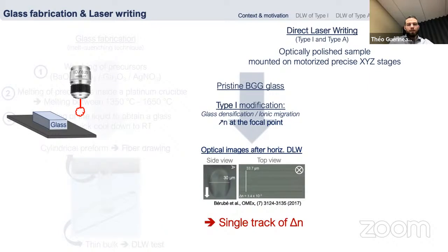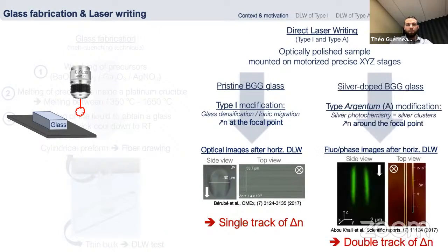So in this case, we have the formation of a single track of the refractive index change. Now, when we dope our BGG with silver, we go to the type Argent, the type A modification. Through silver photochemistry and the generation of silver clusters, we now increase the refractive index only around the focal point. On this picture, you see the side view after the horizontal direct laser writing process.